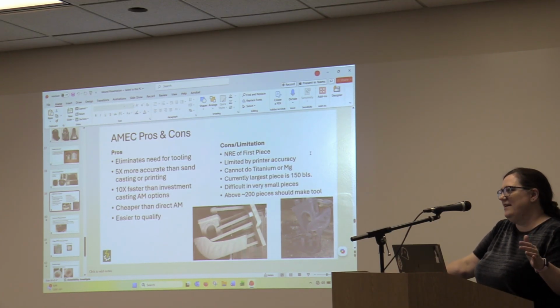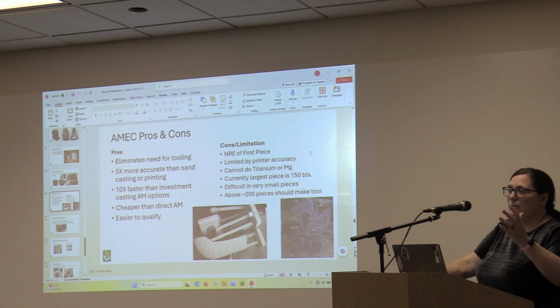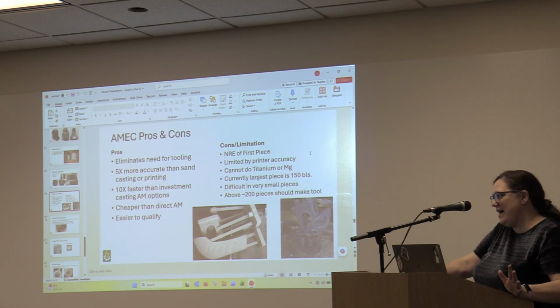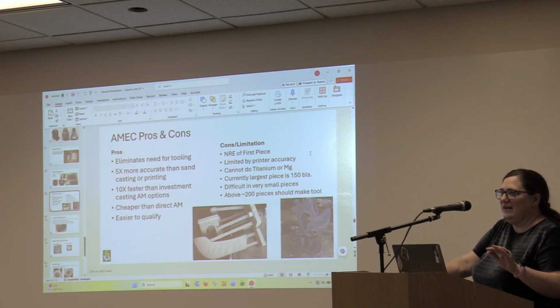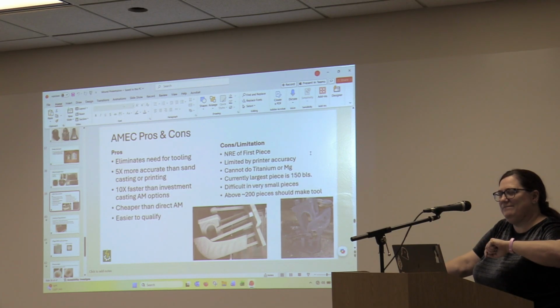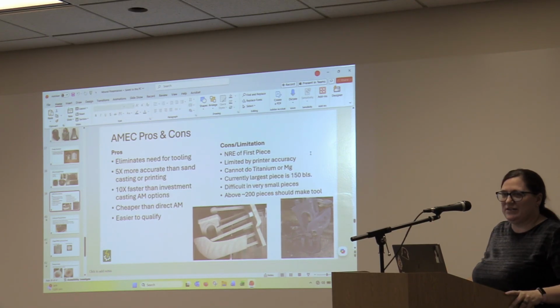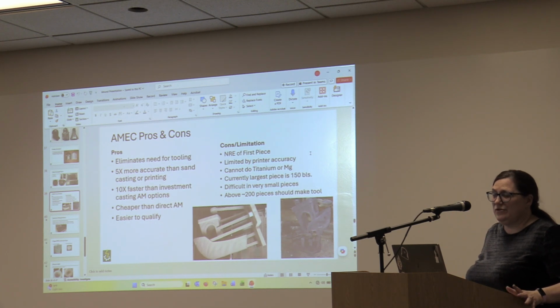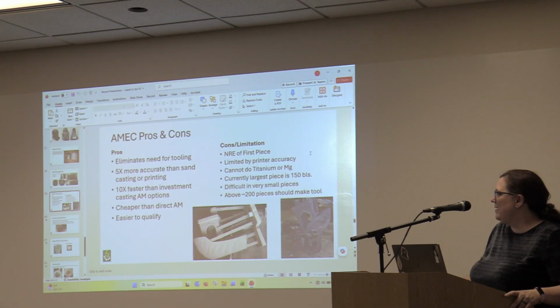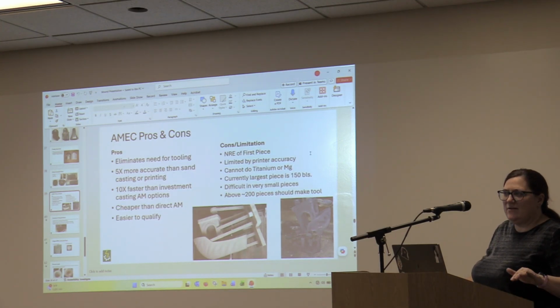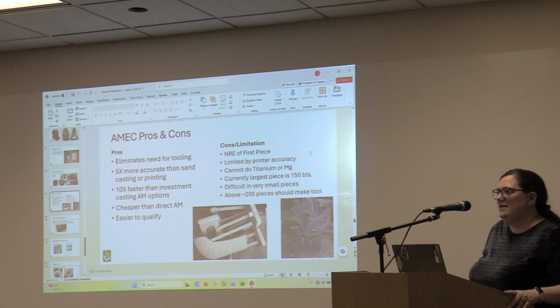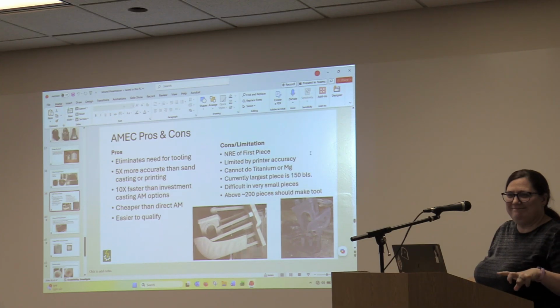But the other way that it's better is it's much faster. Instead of taking weeks like in traditional investment casting or additive investment casting, or binder jet printing, where it still takes a long time to build up that big structure, we are only having to print the surface for the most part, so it's a much faster printing process. We've made AMEC parts in 11 hours, that's the fastest we've done, and in regular lost foam we made parts in about 3 hours.